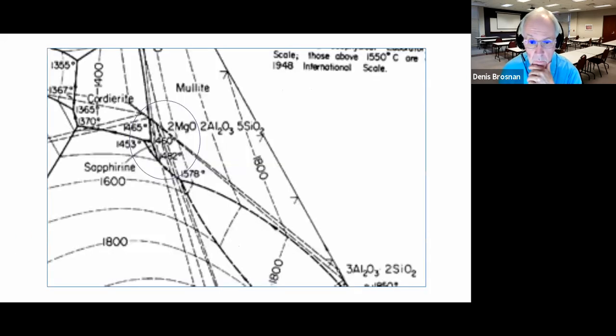And I've blown this up a little bit. Cordierite is 2 moles of magnesia to 2 moles of alumina to 5 moles of silica. There's the line for cordierite composition right here. And that's where you want to be, right in the middle of that circle, right on that line of solid solution. If not, you're going to be in the compatibility triangle with cordierite and mullite and silica, or one of these other compatibility triangles. The other one down here is going to be cordierite, alumina, magnesium aluminate. So those are your choices.